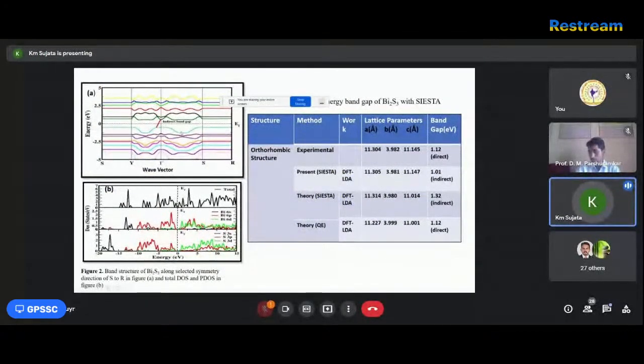This is the band structure and density of states. The band structure calculation within LDA was plotted with the Fermi level at 0 electron volt on the energy scale. Here our material shows an indirect band gap, and the value of the band gap is 1.01 electron volt. This is compatible with other results reported in articles.